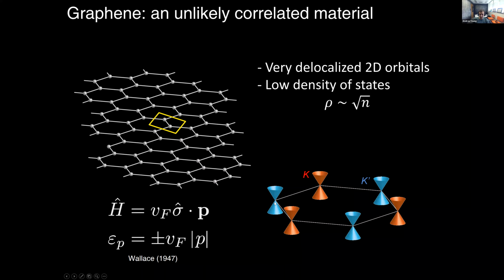It's something that gets taught in most intro condensed matter classes because it's a rather clean way to illustrate band structure concepts. But for his benefit, the basic physics here is that in monolayer graphene, your low energy band structure consists of these two inequivalent Dirac cones, where the elementary excitations are described by massless Dirac fermions, where rather than the physical electron spin, you have a kind of pseudo spin that's related to the relative phase of the electron wave function on the two inequivalent sites within the graphene unit cell.